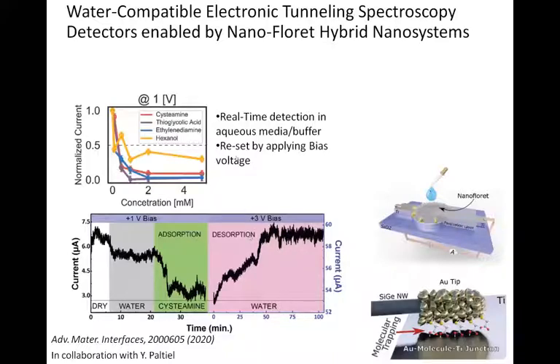So you get that once you put molecules that have specific affinity to the gold tip, the currents diminish as you increase the molecule concentration. This is kind of conventional; you could do this with any conventional sensor. It's nice, but not very interesting. What else could you do? You could do real-time measurements and follow the adsorption. And if you look very carefully, you'll see a kink here. This kink is not noise. This is a reorientation of the monolayer as a change of coverage, where this sensor is very sensitive.